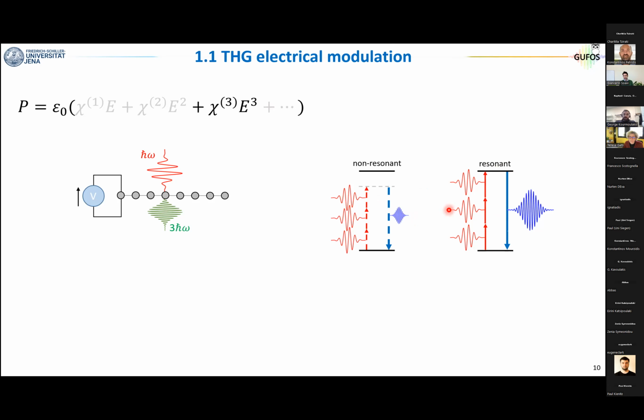Now, you immediately understand that if you try to do this in a semiconductor or a gas, there is no way that you can change the gap, and the only way that you can use to tune the efficiency is to change the fundamental photon energy. Instead, we are looking for a device where we fix the photon energy, so we fix the light that we shine on the material, and we change the efficiency by applying a gate voltage.